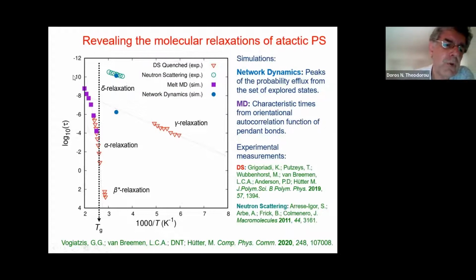On the same plot, I show you relaxation times that were obtained for the melt above the glass transition temperature through this process of observing the orientational relaxation of characteristic vectors on the chains. And we have this characteristic non-Arrhenius dependence that we mentioned, shown by these purple squares. And that again seems to be representative of what experimentalists measure as the alpha relaxation, which is associated with the glass transition. So this landscape picture allows us to go to lower temperature and observe at least the segmental subglass relaxation processes that are present in a glass. And hopefully, if we run long enough, this may even give us the beta and even the alpha relaxation within the glass system, which is completely impossible to get by molecular dynamics.